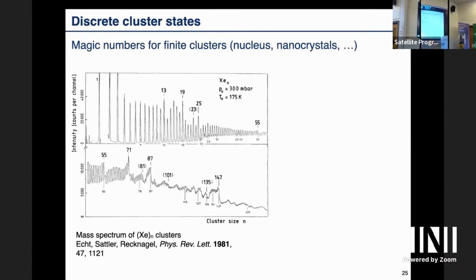So the peaks are the individual states. For every single number of particles in the cluster, you have a peak, and you see some special places. So 13 is a little bit higher. And then at 55, you see a drop off. So apparently something happens at 55. And then if you continue over here, you see another drop off at 147.